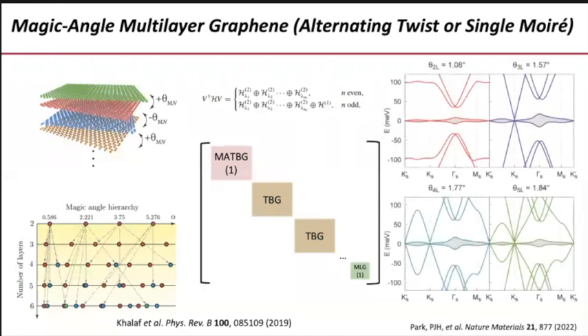So for the electronic structures: for two layers, the magic angle is about 1.1 degrees, and you have just a flat band. For three layers, you have the flat band plus a monolayer Dirac cone. For four layers, you have the flat band and a large-angle twisted bilayer graphene block. For five layers, you have flat bands, large twist angle, plus a monolayer Dirac cone, et cetera, et cetera.